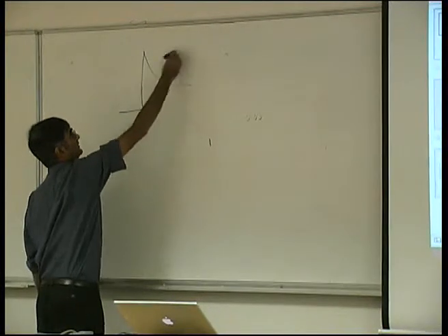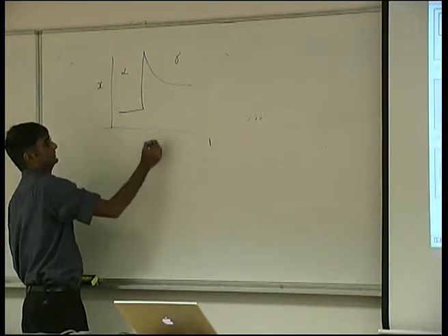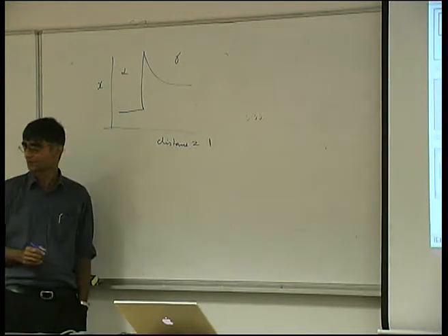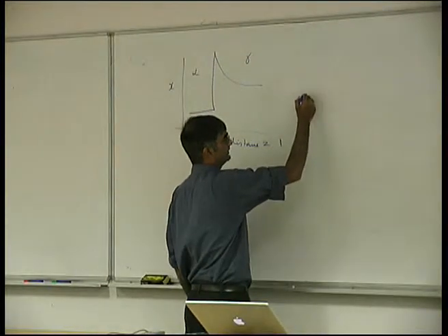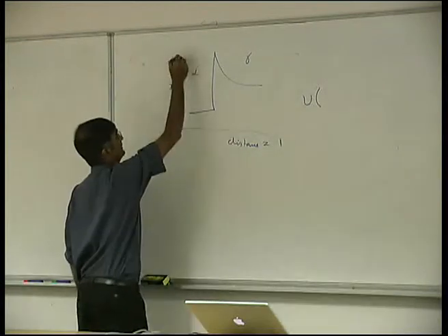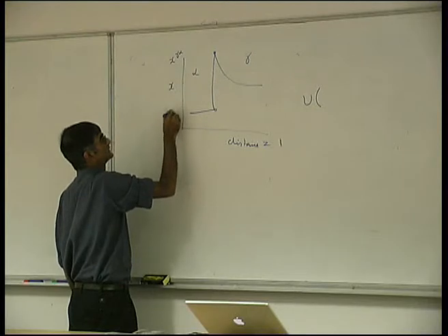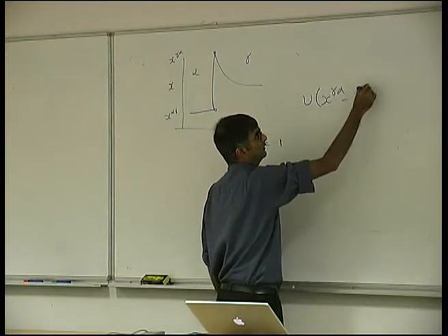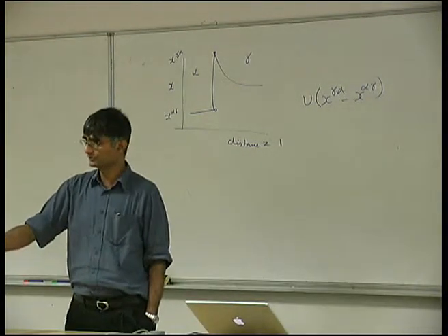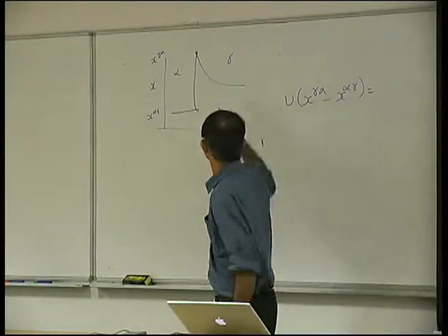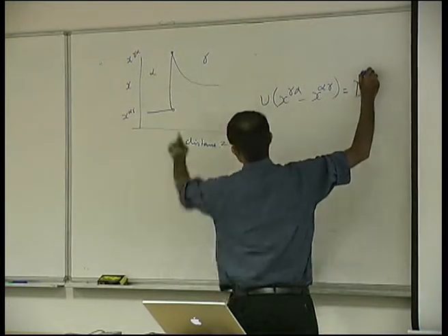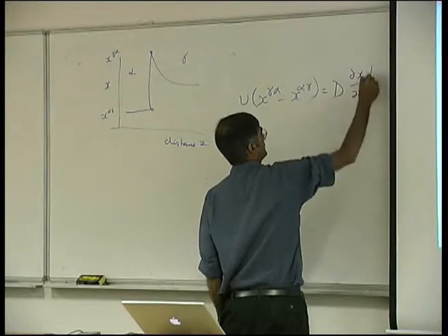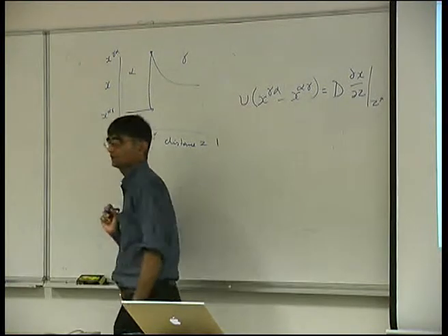And if you remember, we had an equation which says that, supposing this is a phase growing, so this is gamma and this is alpha, we are plotting concentration x versus distance z. In this case, alpha is solute depleted, so we are getting a build up of solute in the gamma. Then we had an equation which says that the rate at which solute is being rejected is the velocity of the interface times x gamma alpha minus x alpha gamma. That's the rate at which solute is being rejected as the particle grows. It must be equal to the diffusion flux down here. If you are going to maintain these two points constant, that must be equal to the diffusion coefficient times the gradient of concentration at this point, which is dx by dz at the position of the interface. So that's a binary case.